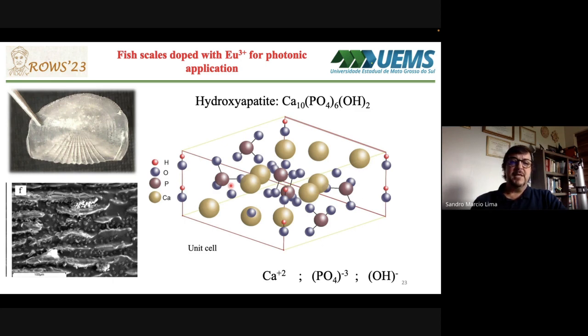So, as mentioned, the scale is also composed of a single mineral phase of calcium deficient hydroxyapatite in the apatite phase. Its structure is formed by a tetrahedral arrangement of phosphate in the unit cell, which is composed of 44 atoms of inorganic groups, such as calcium 2+, phosphate, and hydroxyl, arranged in a hexagonal shape. Some studies have shown that hydroxyapatite has high porosity, which is a key property for different applications.